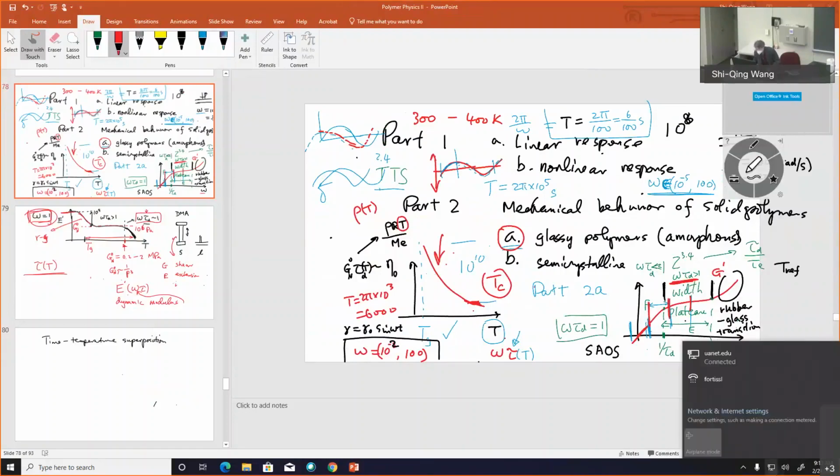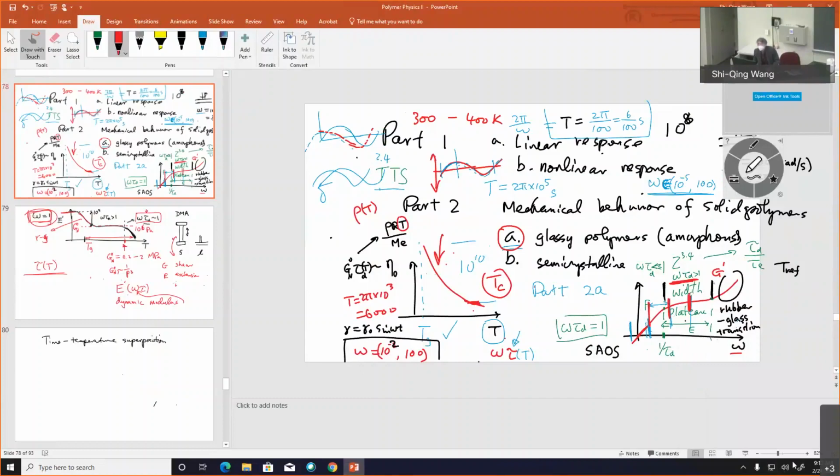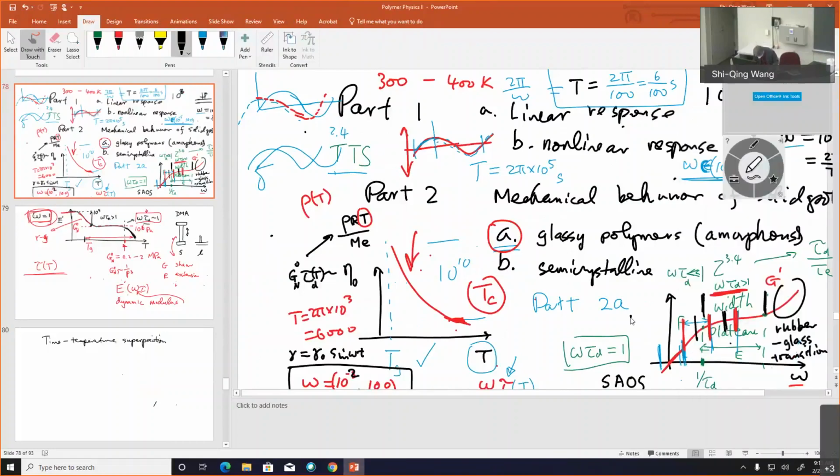So when I do the next one, I don't do it here like that. I do it like that, so that there is this region where the two sets of data will overlap. I need that to confirm that they match in a region they both share. So in this sense they are superimposing onto each other, and keep going.